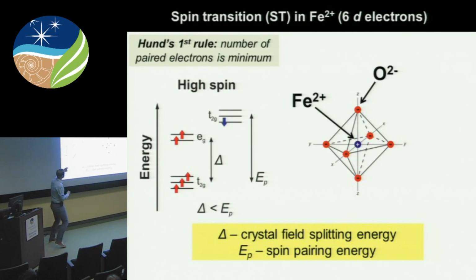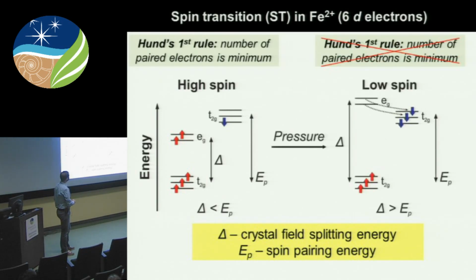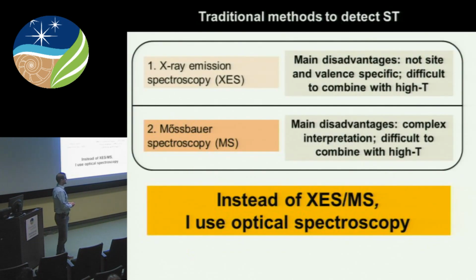However, you can apply pressure on this system and effectively change this delta. Basically, you can think of squeezing on these oxygen atoms. As they come closer to iron, they will cause more electrostatic repulsion on the iron d electrons, and as a result, delta will increase. So you will increase the separation between the T2g and Eg levels, and at some point, delta will become larger than the pairing energy, and that's the moment when Hund's first rule doesn't work anymore, and your Eg electrons basically jump down to the T2g level to pair with the d electrons that are already sitting there. So that's what we call low spin configuration, and this is what we call high spin configuration. And this kind of transition is what we call a spin transition.